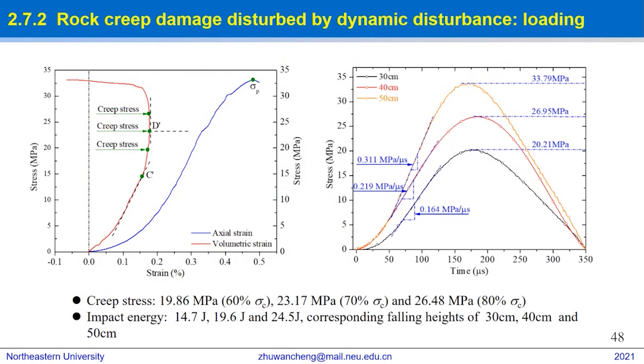Prior to performing creep experiments, quasi-static tests at a strain rate of 1×10^-5 per second were conducted to obtain the stress-strain curves of the sandstone. A representative stress-strain curve is shown at the left figure. Stress waves generated by the hammer falling from heights of 300, 400 and 500 mm are shown at the right figure, where the peak stress and the loading rate are indicated.